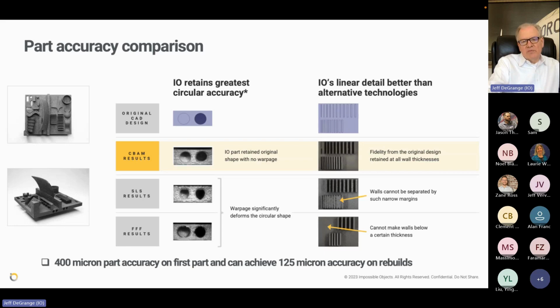Another thing I will mention, a typical question asked about a new material and process is what's your part accuracy? Well, if we took a customer part and built it as is, we would feel comfortable saying that it's usually within a 400 micron part accuracy on the first part. But if you needed better tolerance than that, we could apply a scale factor, do a rebuild, and get close to about 125 micron accuracy. And that's true for a lot of additive processes, but these are the accuracies you can achieve with the CBAM process.